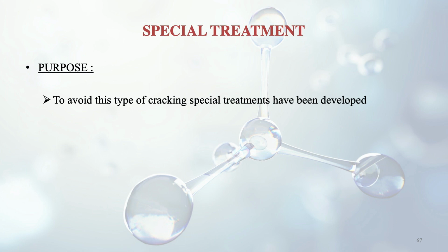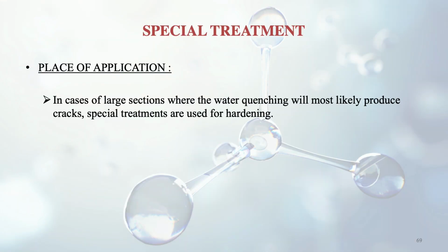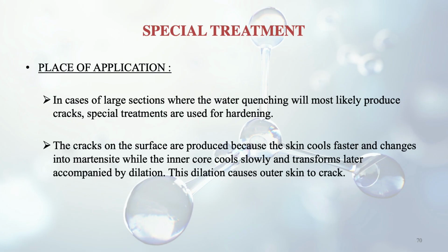So now we discuss some special treatments after discussing the tempering process, and why this special treatment is needed. The purpose is to avoid any types of cracking. That's why we give these types of treatments. They are applied in case of large sections where water quenching will most likely produce cracks, and therefore we will do a special treatment. And why do these cracks appear actually? Because the skin cools faster and changes into martensite, while the inner core cools slowly and transforms later, so dilation occurs. So this dilation causes the outer skin to crack.